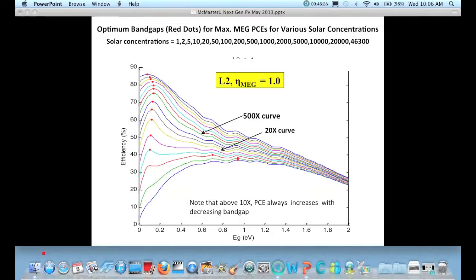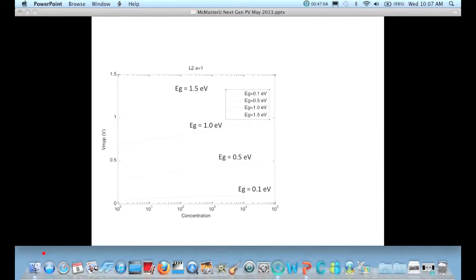The Shockley-Queisser analysis shows that the optimum band gap shifts far to the red. These red dots represent the peak of the Shockley-Queisser analysis, and show that if you had a band gap of 0.2, that's when you get the highest efficiency, and that's really small. But the idea is that 0.2 could give you 10 electrons per photon. If you take the average energy of a photon in the solar spectrum as 2, and the band gap is 0.2, that means a photon with 2 energy can give you 10 electrons. So we'll skip some slides.